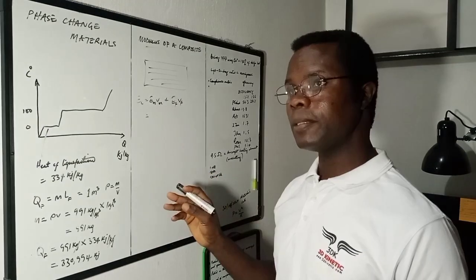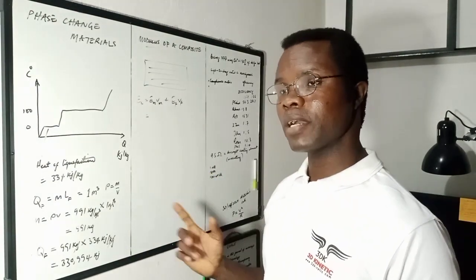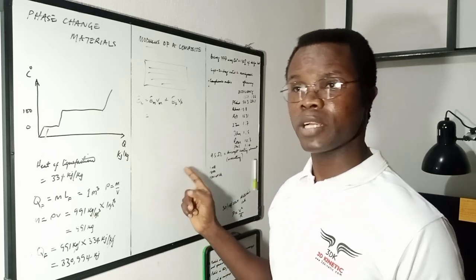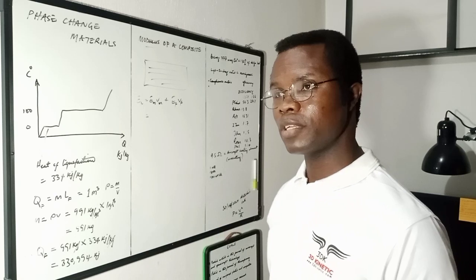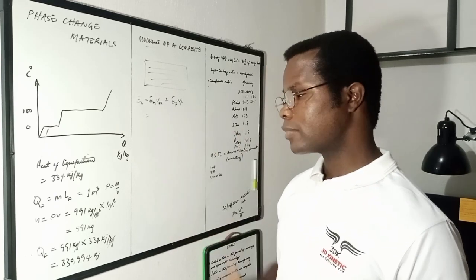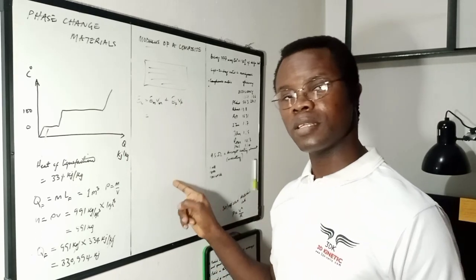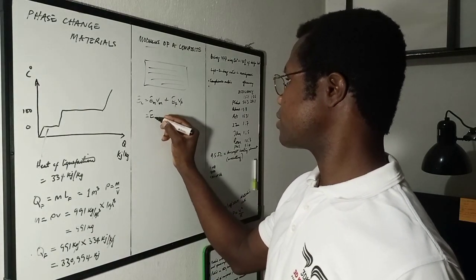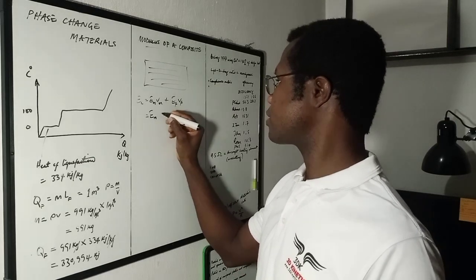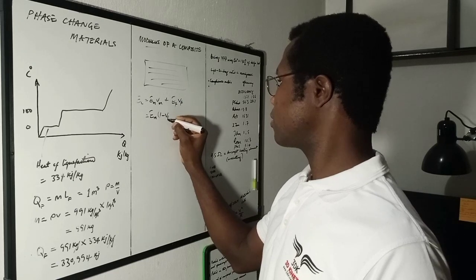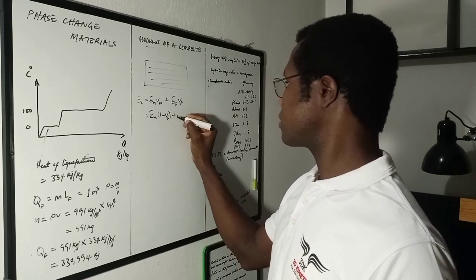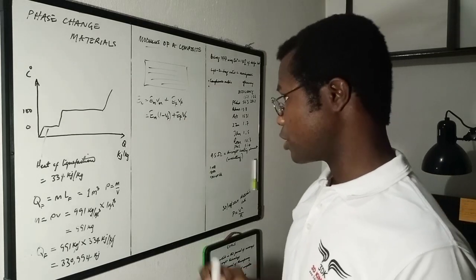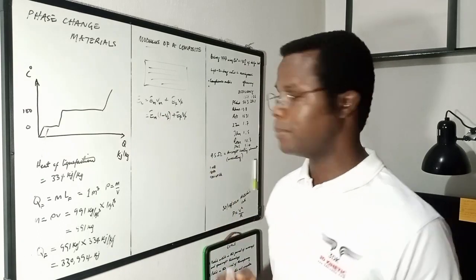So the volume fraction of the matrix is equal to 100% of the composite minus the volume fraction of the fiber. If you want to obtain the volume fraction of one, simply subtract the volume fraction of the other from the whole, which is why it's easy to rewrite it like this. So modulus of the matrix times 1 minus the volume fraction of the fiber, plus modulus of the fiber times the volume fraction of the fiber. I'm sure this is clear enough. Vm is equal to 1 minus Vf is what I was explaining.